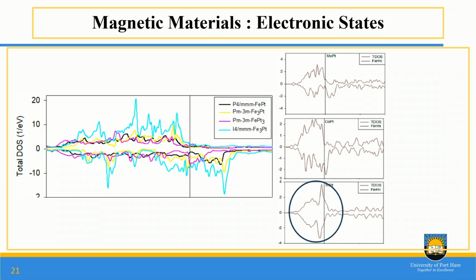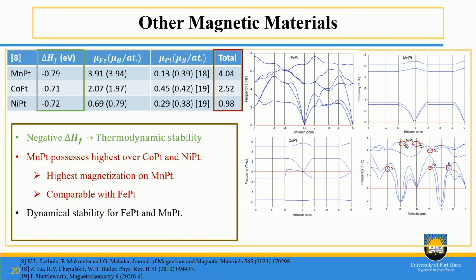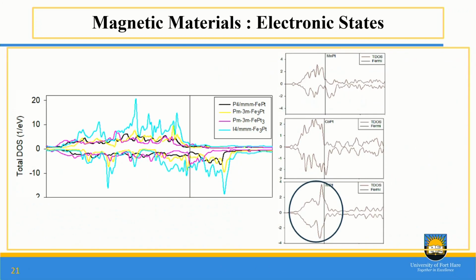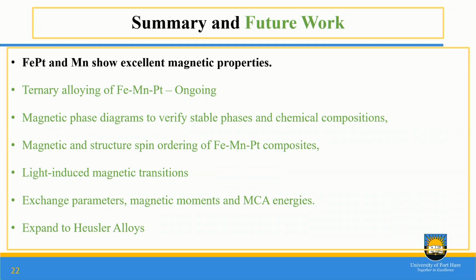Normally the electronic structure tells us how large the magnetic moments are going to be. Let's just look at the last one, which is nickel platinum. It has the least magnetic moment. You can see that the spin up states and the spin down states are almost symmetrical, almost the same. That means their magnetic spins are almost canceling each other, hence it has the lowest magnetic moment. So this is what we can conclude about the magnetic alloys: we have found FePt and MnPt to show excellent magnetic properties.